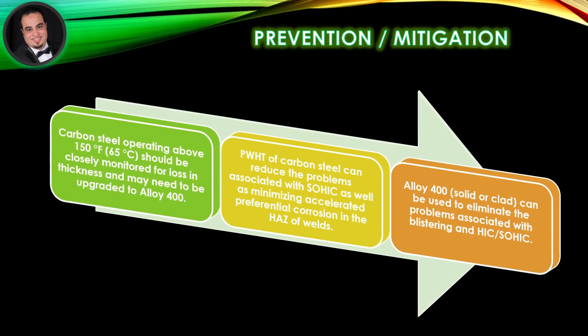Prevention and Mitigation: Carbon steel operating above 150 degrees Fahrenheit should be closely monitored for loss in thickness, and may need to be upgraded to Alloy 400. Post weld heat treatment of carbon steel can reduce the problems associated with stress-oriented hydrogen-induced cracking, as well as minimizing accelerated preferential corrosion in the heat affected zone of welds.